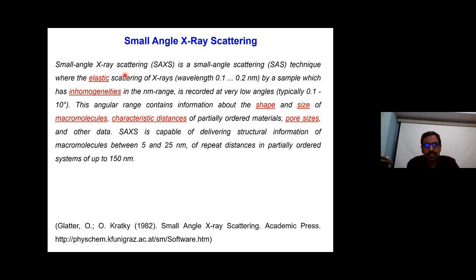And what they say is that small angle X-ray scattering is a small angle scattering technique where the elastic scattering of X-rays between 1 to 2 angstrom by a sample which has inhomogeneities. These words are important: elastic scattering and samples having inhomogeneities. When I say inhomogeneities, when I'm talking about X-ray scattering, it means the difference in electron densities within the sample. So the electron density differs as you move within the sample. Okay, and inhomogeneities in the nanometer range are observed.